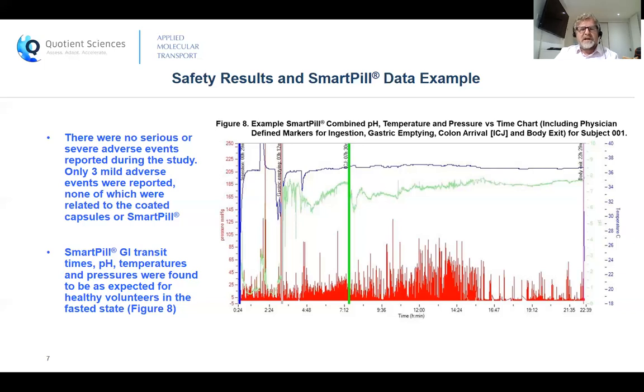It can be seen that pH rises rapidly from around 1 to 7 upon gastric emptying, whilst there's a typical drop in pH coincidental with a pressure profile change at the point of colon arrival. The overall smart pill GI transit times, pressure, temperatures and pHs were found to be as would be expected for a healthy volunteer population in the fasted state.